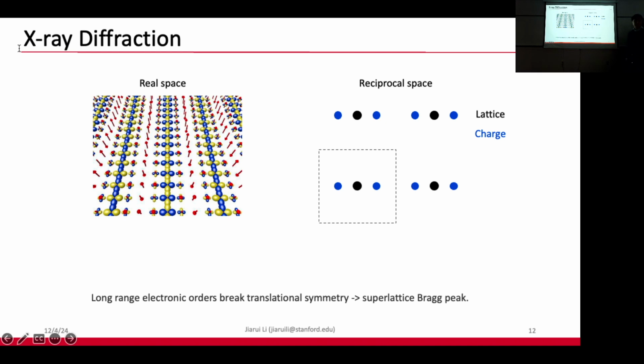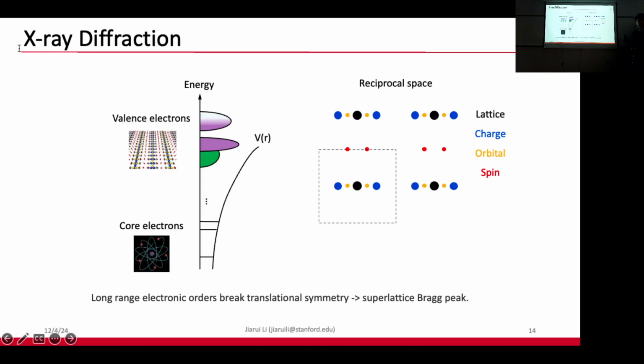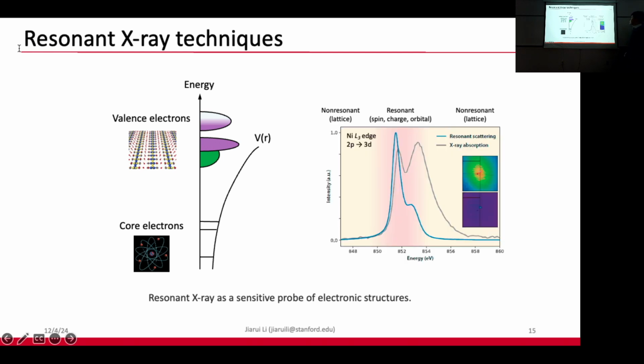of this reciprocal space. And if you do similar considerations for the magnetic degrees of freedom or orbital degrees of freedom, you will see additional orbital or spin Bragg peaks. And this is theoretically working, but actually you wouldn't see that in a lab environment. The reason is that the interesting electrons that participate in these complex electronic structures only exist in this valence band. And in the diffraction process, most of the electrons are concentrated in the core electrons, which is here. So the signals coming from these charge, orbital, and spin degrees of freedom are very weak compared to this lattice.